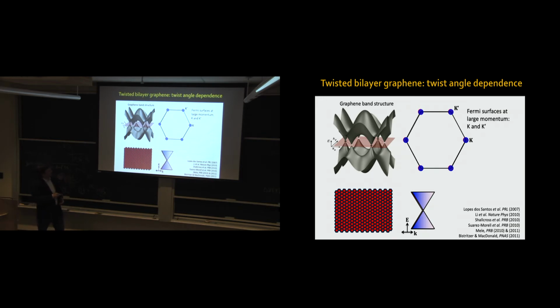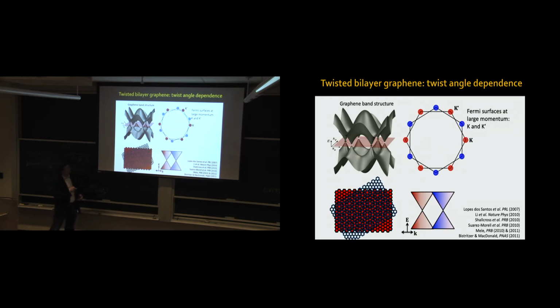If I rotate the 2 graphene sheets, the reciprocal spaces also rotate by the same angle. This means the Dirac cones, the Fermi surfaces associated with my Fermi energy, get separated in momentum space. Because it's 2-dimensional, I have a Fermi surface which is a disk. Twisting these two layers of graphene leads to Dirac cones representing the energy-momentum relation of electrons in one layer and the other. They get separated in momentum space by a distance proportional to the sine of the angle.